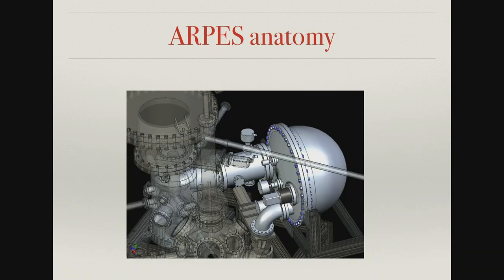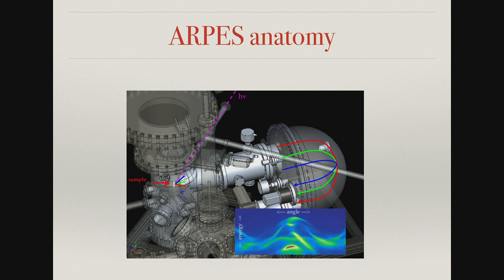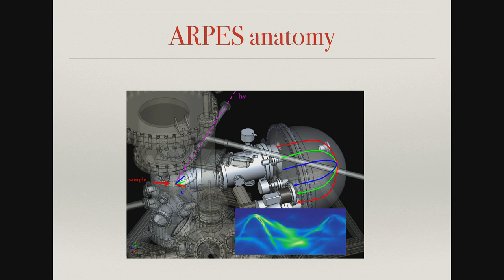At the end of one of the beam lines this apparatus is installed at BESSY II, and we can cool down the sample to very low temperatures. The beam coming from the synchrotron allows us to detect electrons emitted at different angles to different positions, because the analyzer is placed in the focal plane of an electronic lens. These electrons are then analyzed in terms of energy. Simultaneous analysis allows us to see the distribution as a function of momentum and energy in one image, and if you then move the sample you can scan through the band structure of a solid, changing several parameters.